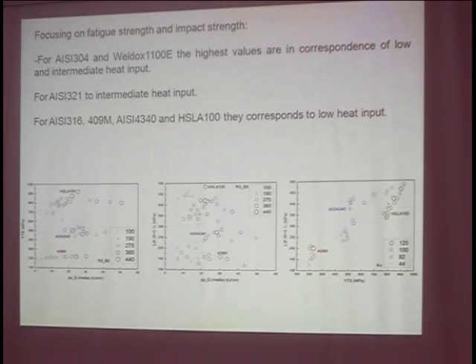And here you can find some examples for some single steels, because after the global evaluation, we focused on each single steel to optimize each single situation. Focusing on mechanical properties for AISI 304 and Weldox 1100E, the highest values correspond to low and intermediate heat input. For lower heat input, you have a strong decrease in mechanical properties. For AISI 321, the optimum is for intermediate heat input. If you have a very high or very low heat input, mechanical properties decrease strongly.